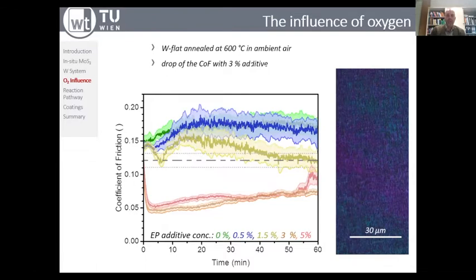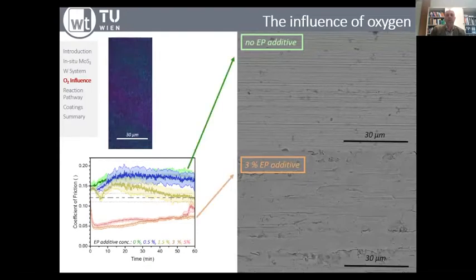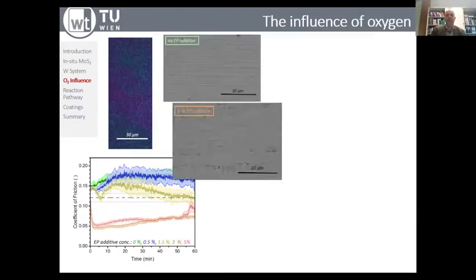And obviously, this approach of pre-oxidizing the tungsten surface had an effect on that. Now we have to understand why. So there are actually two parts, initial reaction and breakthrough reaction, if we look a little bit deeper at that. Again, you see the wear tracks or the micrographs for no EP additive and 3% EP additive. And if you then do XPS and EDX on the oxidized surfaces, you can learn quite a lot.